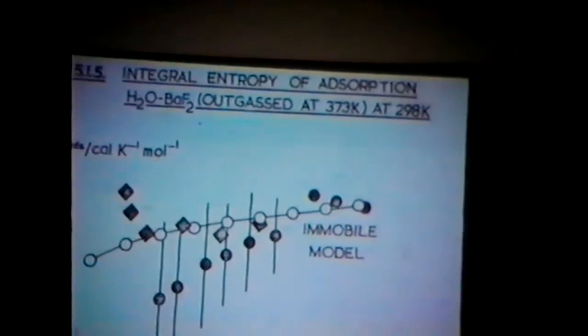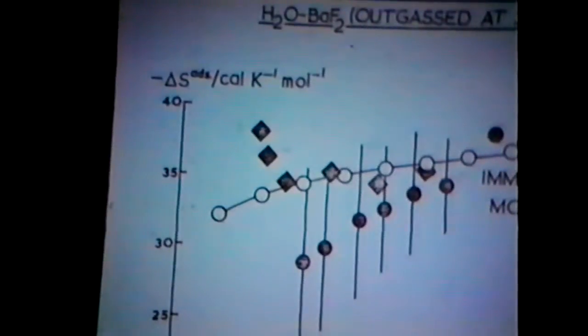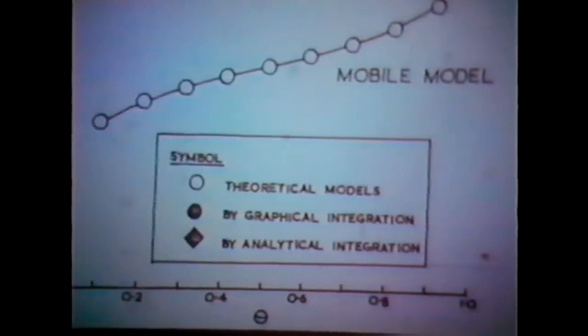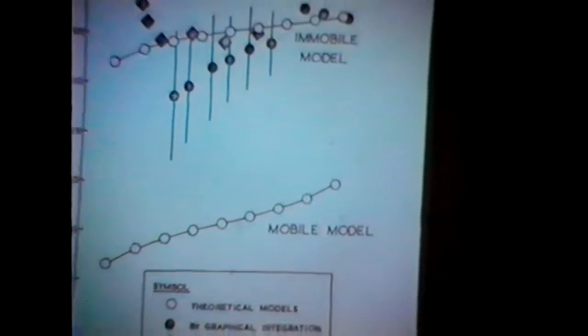We've used these occasionally. The best method, we think, is following the procedure published many years ago by Emmett and Hill, and I forgot the other one now. Joyner. Where the method is essentially to integrate the Gibbs equation, and that means you've got to have quite good data down to low pressures. That tests out whether you've done the isotherm. They're fairly low pressure.